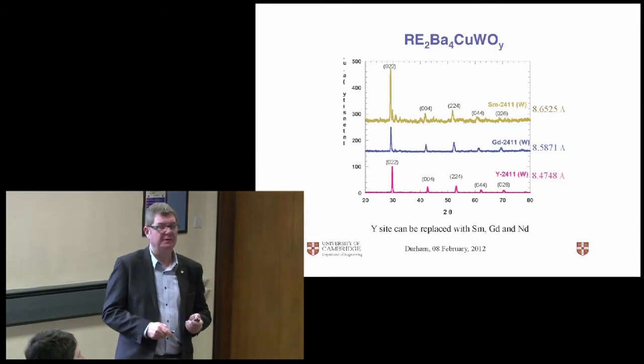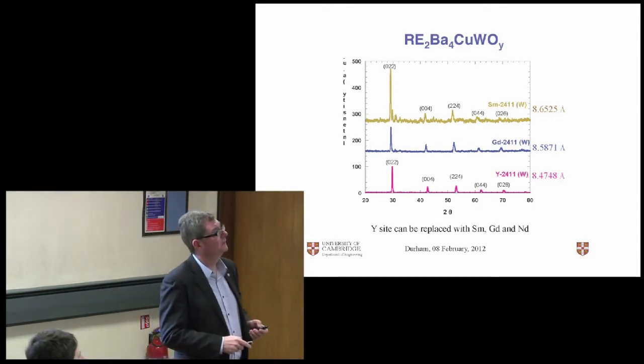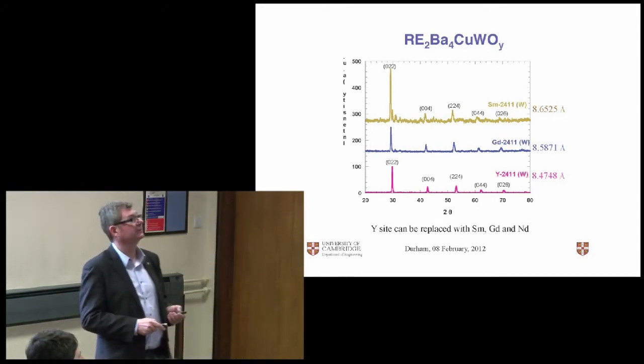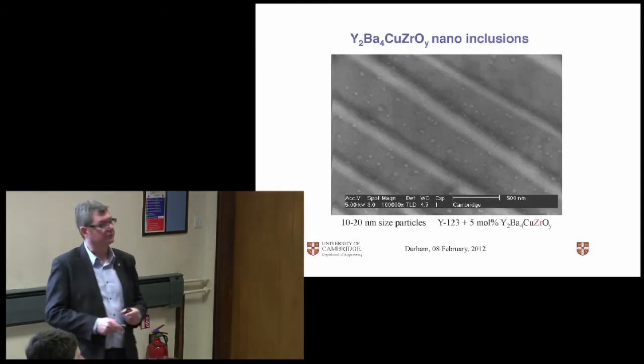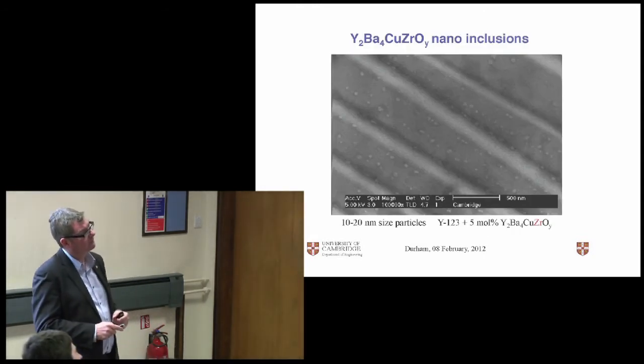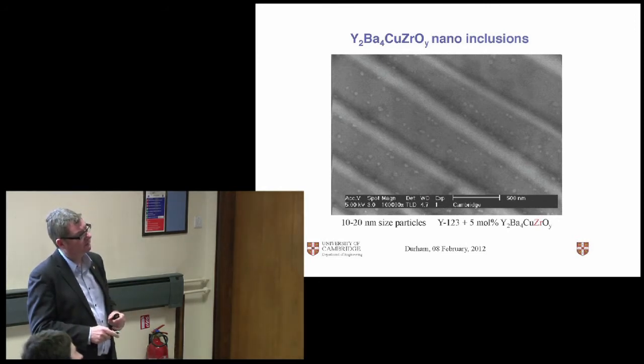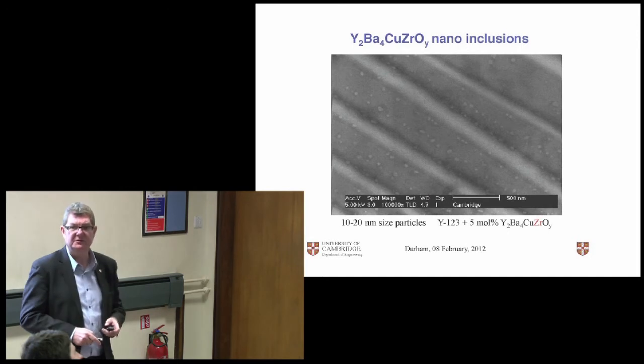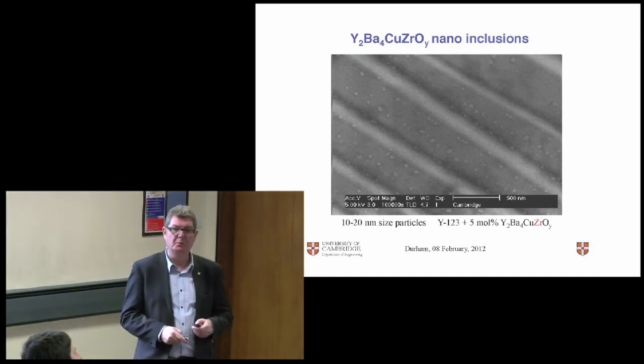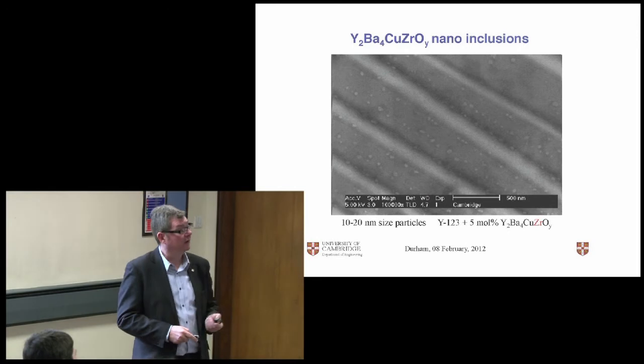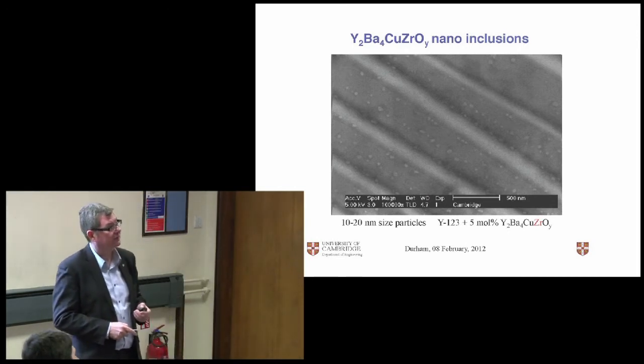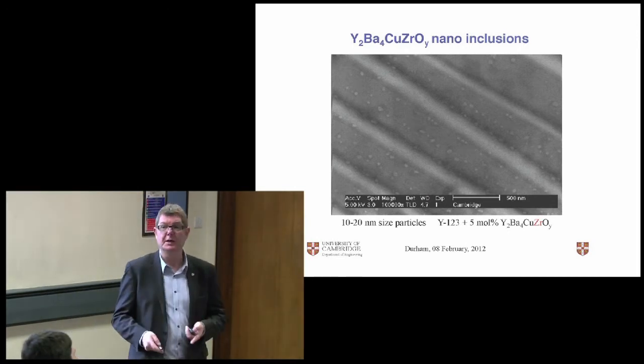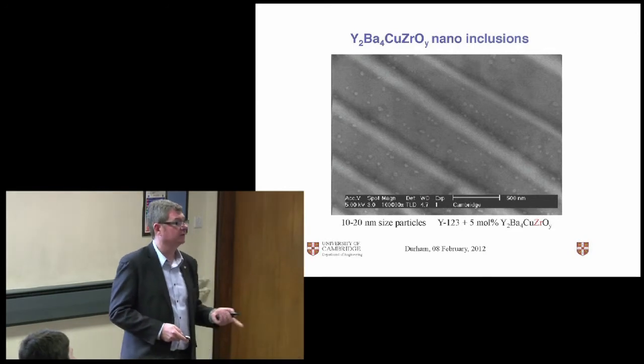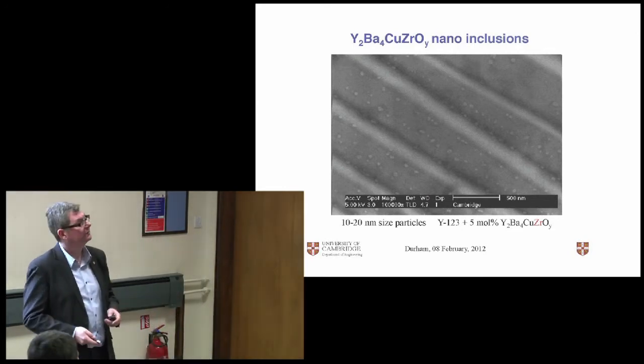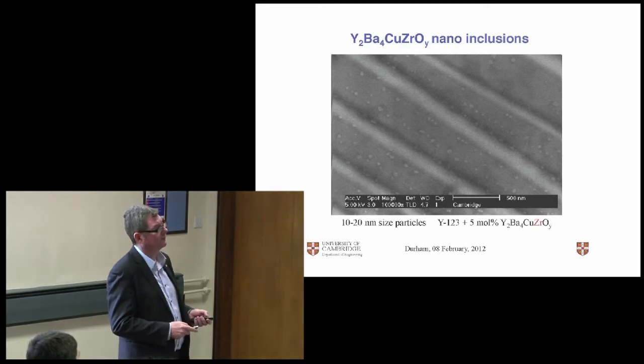So this then was a very promising flux pinning centre, a very novel one. Again, we patented it. Let me just show you the microstructure. Here we've got the zirconium variation of 2411, and you get these tiny second phase inclusions of the order of 10 to 20 nanometers. Remember, 211 is 1 to 10 microns, and the smaller you make these pinning centres, the better. You want them of the order of the coherence length of the superconducting charge carriers, which is round about tens of nanometers. So this looks very good.